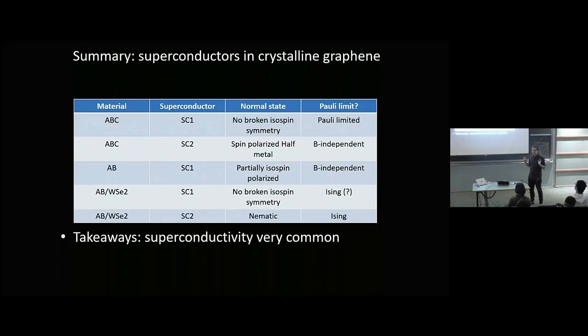So that's just from an empirical point of view. I think it's a point that I want to make really strongly, which is that in these systems, you get superconductivity, and it's anywhere from 30 millikelvin Tcs to 500 millikelvin Tcs, sort of the largest that's been observed, and they appear all over the place, and there's not much rhyme or reason to it as far as I can tell. So I tend to lean that, if there's a mechanism that underlies all this, it has to be something extremely generic, which kind of leaves two possibilities, I think.